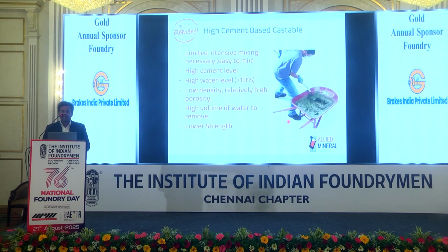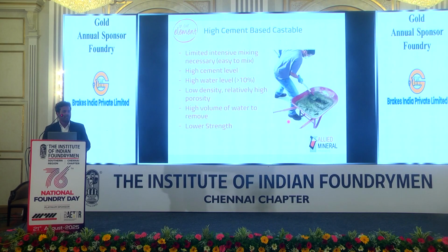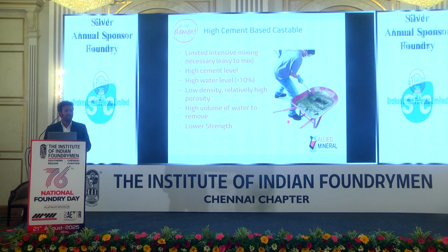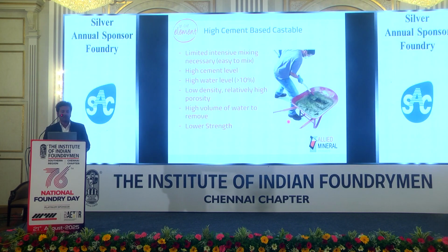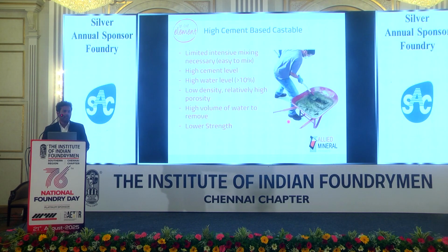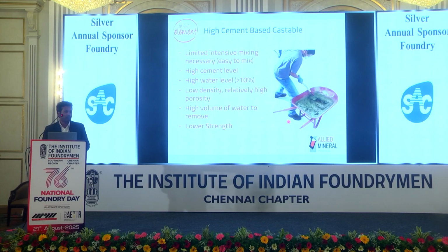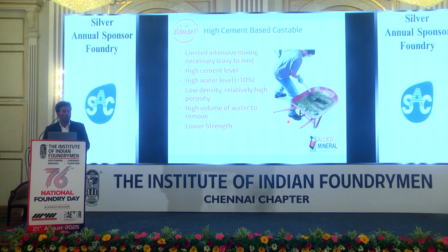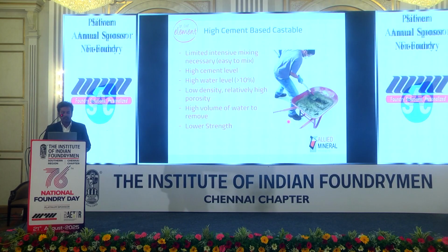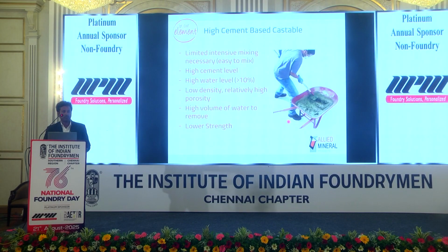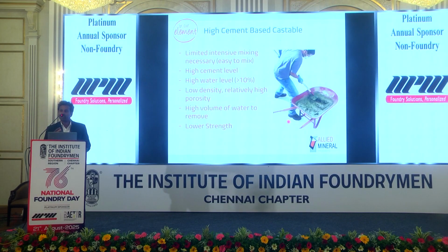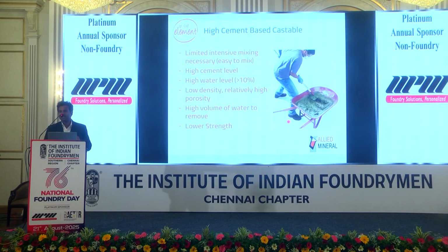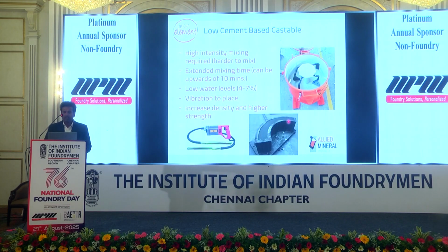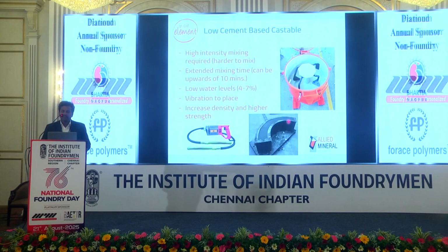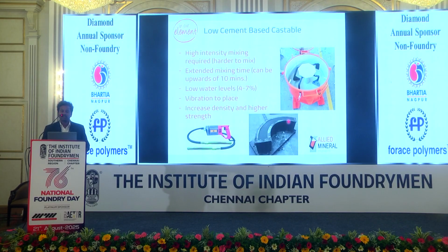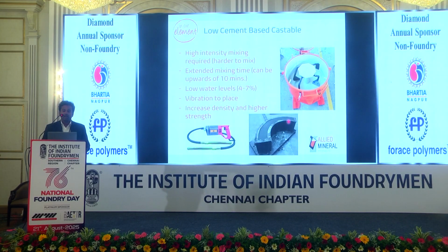When you see the high cement based castables, it requires less intensity of mixing, and a high level of cement. When the cement level is high, obviously the water percentage will be more. So the density goes down, and a lot of water is in the system. It's always difficult to take all the water out of the system, and it has very little strength. On the other hand, low cement based castables are the best suitable system for your ladle refractories.